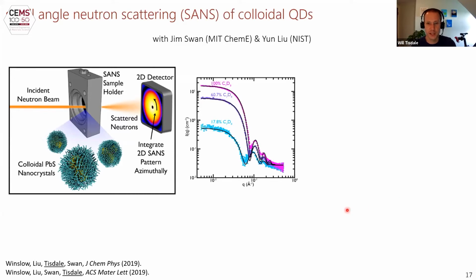So this is the scattering intensity as a function of scattering angle, where we varied the deuteration fraction of the toluene solvent in the suspension from 100% deuterated solvent to about 20% deuterated solvent. One of the striking things you see here is all we're changing is the deuteration fraction, but the location of the dominant scattering peak is actually changing. We don't think that the quantum dot is changing in size. There's no reason to expect that. What this is telling you is it's informing on solvent penetration into the ligand shell that's on the surface.